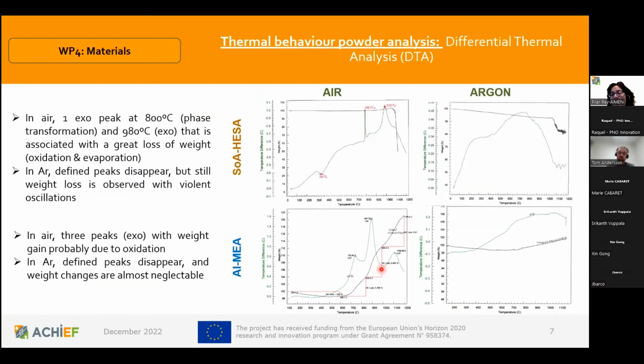Also, we perform some analysis using DTA in order to know what is the behavior of these 2 alloys, both in air and argon, and we get some interesting results. Above all, comparing both materials in air, because with the first material we get some peaks here, but the problem is that these peaks are associated with a large loss of weight. That is something that we cannot see here in the second material, in which the peaks are associated to the oxidation, but with a weight gain instead of loss. This kind of DTA can be associated with the problems that we'll explain later during the manufacturing.